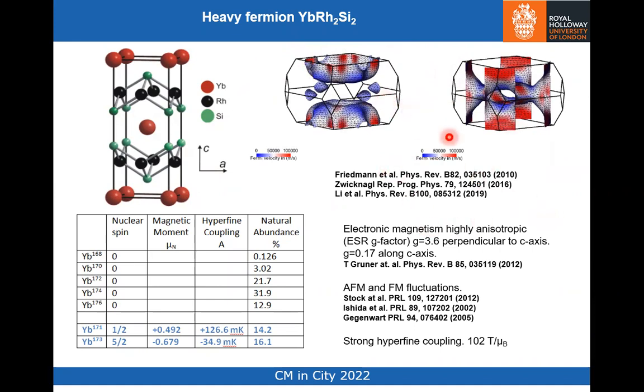So important characteristics of this material is that the electronic magnetism is highly anisotropic. Remarkably, it shows a sharp ESR resonance in the heavy fermion regime. That's attributable to the presence of ferromagnetic spin fluctuations, according to a theory by Abrahams and collaborators. The g factor measured by ESR is highly anisotropic, so it's 3.6 for the field along the c-axis and 0.17 along the c-axis, so 3.6 perpendicular to the c-axis. I misspoke, sorry for that. And this anisotropy reflects the highly anisotropic nature of the pseudo-spin ground state doublet of the ytterbium moments in the crystalline electric field.